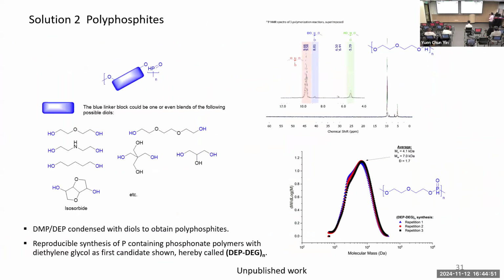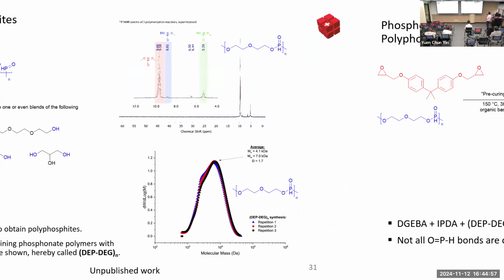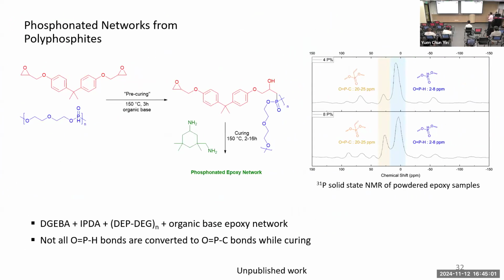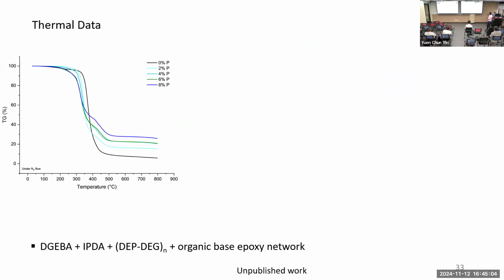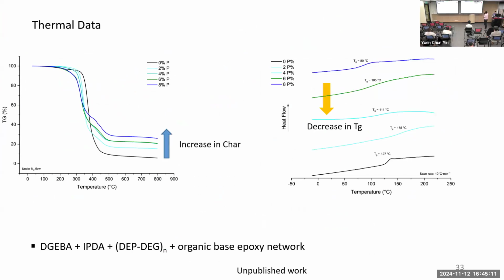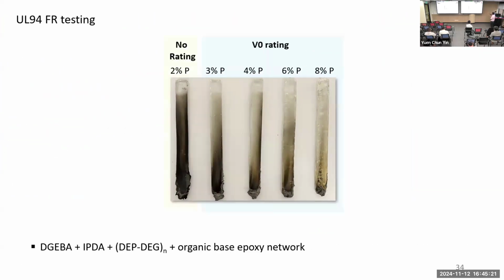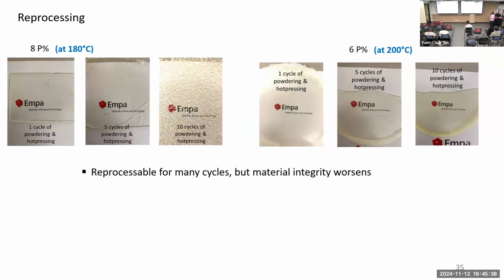We can also resolve the problem by not only making small phosphites, but making polymeric phosphites. And this polymeric phosphite can then react and form resins, I would say. You get more phosphorus, more char, which is very interesting. Obviously, the glass transition goes down the more phosphorus you add, just so you know about the side effect of having these phosphorus species. You get a UL94 V0 very easily. In this case, when you use polymeric phosphorus compounds, you need 3% phosphorus to get a V0, but for recyclability, you need around 4 to 5% phosphorus.